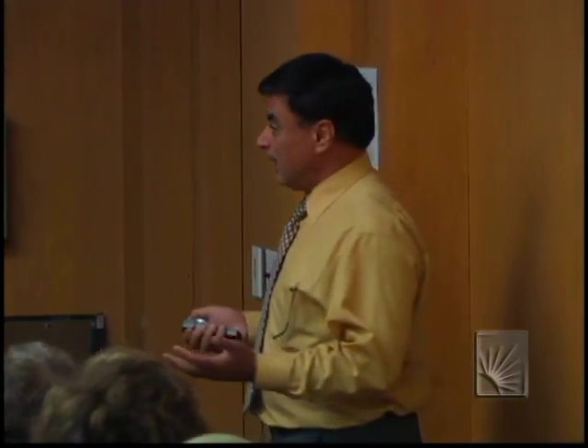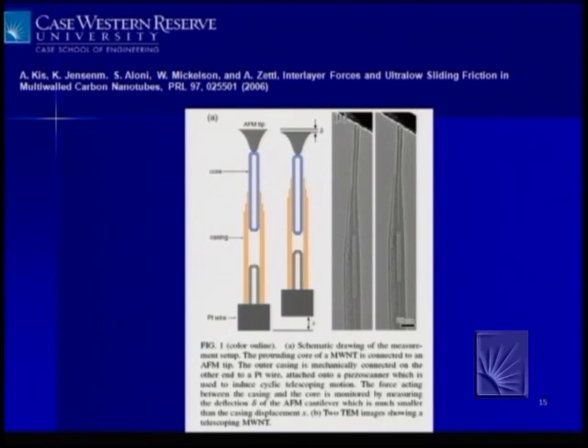So multi-walled carbon nanotubes have some other interesting characteristics. If you hang on to both sides of the carbon nanotube, these multi-walled ones, and pull on them, they start telescoping out. And when they telescope out, these carbon atoms on different layers grind against each other, kind of quantum mechanically. And as they do that, the resistance or conductance between these two posts changes periodically, because these carbon atoms are arranged in periodic arrays. So you can use that as strain gauges with very large gauge factors. And you can use them, for example, to track position at nanometer scale. And there are lots of devices that people are working on.